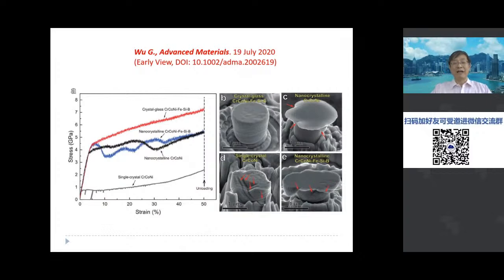Another way to develop this kind of dual phase material is another example, recently published 3 months ago. We have initially a crystal, a so-called high entropy alloy. Then we dope it with some other element so that we can have a glassy property. So we can generate nano glass combined with nanocrystal, and you can see this mechanical property is very good, with very high deformation capacity but also a very strong yield strength. So this new methodology opened the way to develop plenty of new materials.